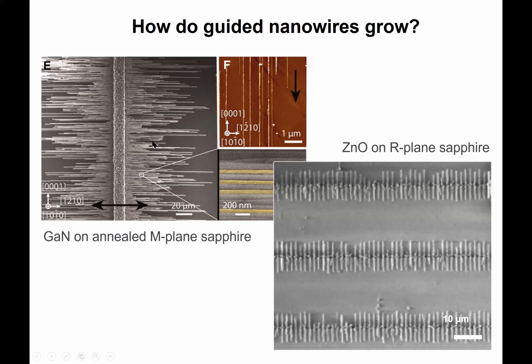For instance, gallium nitride tends to grow very, very long, longer than 1 millimeter, but with a very large distribution of lengths. Zinc oxide, on the other hand, can have a very narrow distribution of length, amazingly uniform, but no longer than 10 microns.